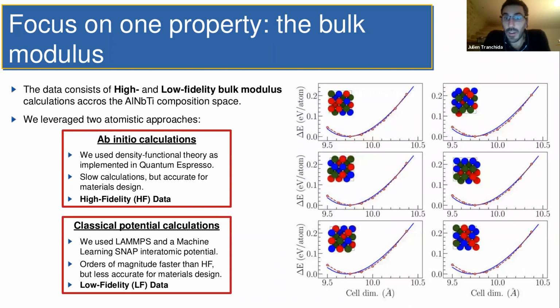And then we're going to be focusing on one property, which is the bulk modulus. So it's basically an entry point work. We wanted to have one quick property that we could compute with both DFT and classical potentials. The bulk modulus is kind of the ideal one, because it's useful to know the bulk modulus of a material as a function of composition, for example, but it's quite simple to compute. So the data here will be high and low fidelity bulk modulus calculations all across this aluminum, niobium, titanium composition space. So we are leveraging two approaches.